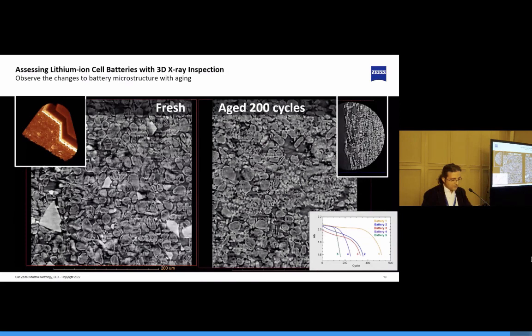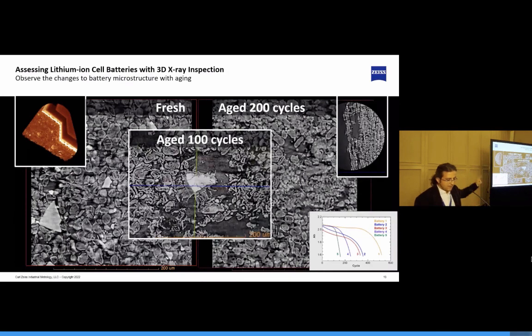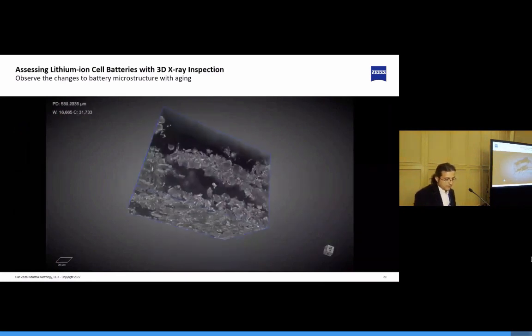So what happened in between? If we scan now an intermediate step, let's say 100 charging cycles, then we see that at that point the silicon particles start to crack and they are pushed away around it. So it disappears after 200 cycles. And these are, again, very interesting information that you can observe non-destructively in the battery.